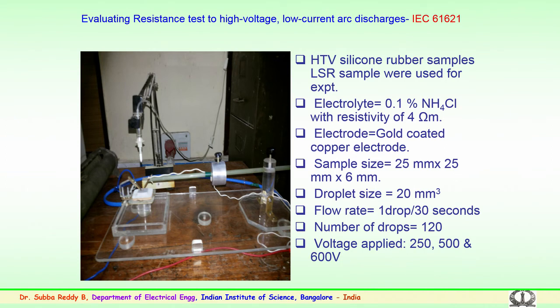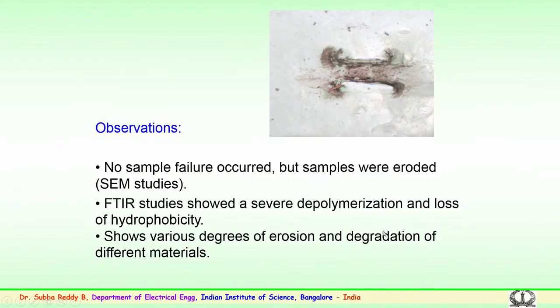The surface changes that happened over the 120 droplets were studied, and the evaluation of resistance was done. So, this is how some of the observations were made: between the electrodes on the sample there is an erosion which has been observed, but no sample failure occurred during the process. All the samples were observed to be eroded when the scanning electron microscopy studies were carried out, and the Fourier transform infrared studies showed severe depolymerization and loss of hydrophobicity, particularly the water repellent activity of the rubber had lost the property.